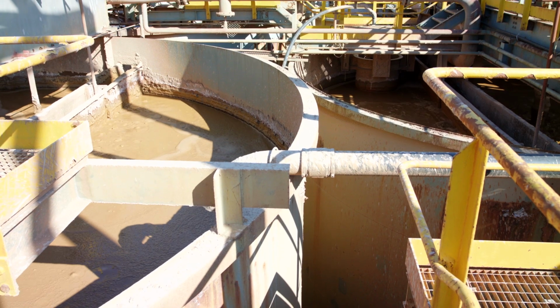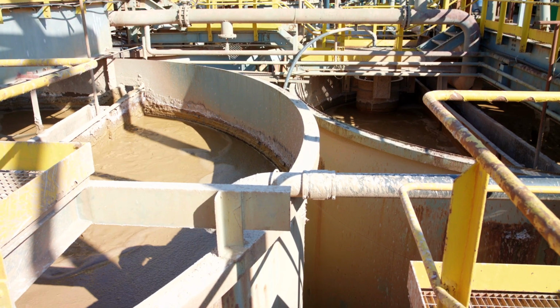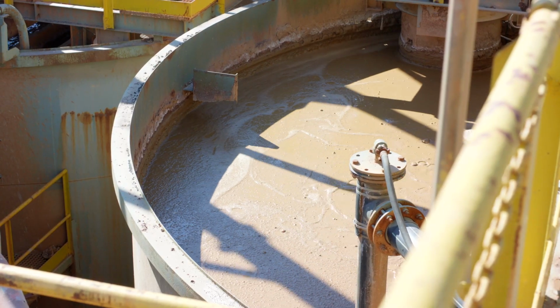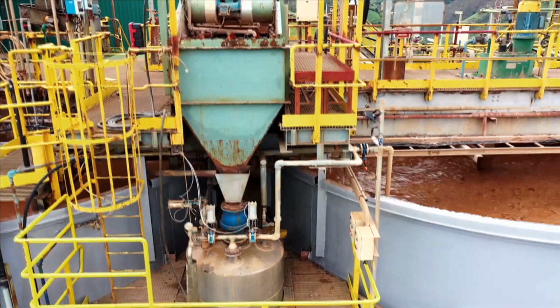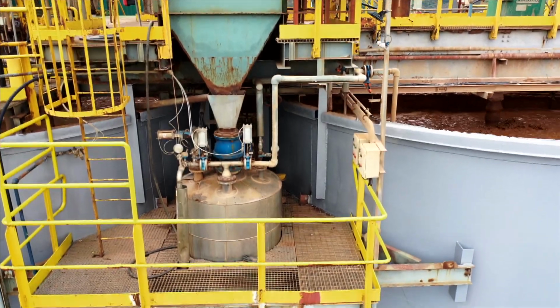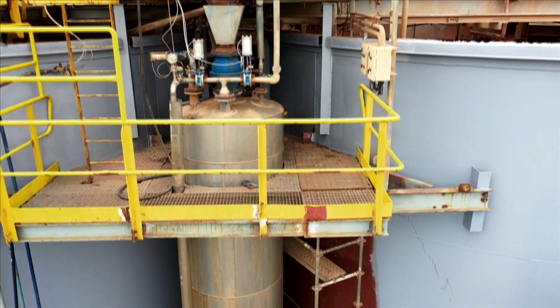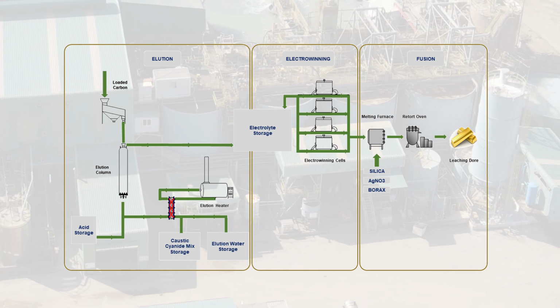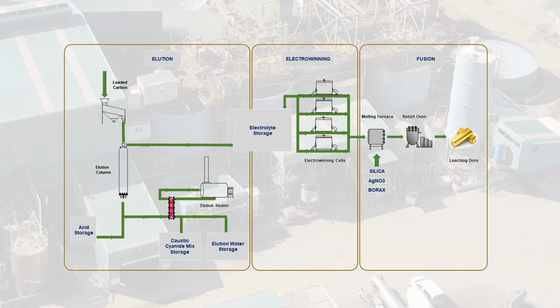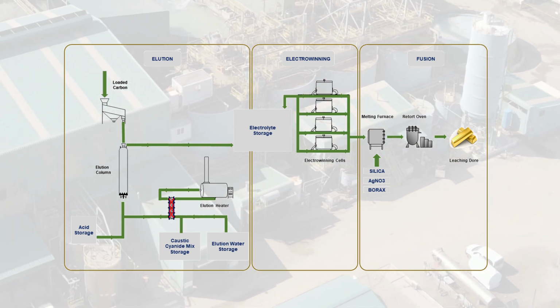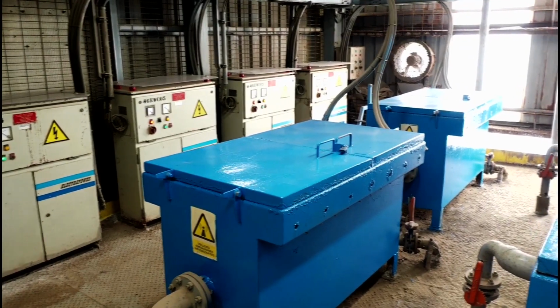The fine gold particles that do not come out through the gravimetric process or by the physical-chemical flotation process are extracted here by chemical reaction with oxygen and cyanide in the CIL circuit. The carbon charged with gold goes to the elution process, from which free carbon and a gold cyanide complex called electrolyte are obtained. The freed carbon goes back to the CIL circuit.